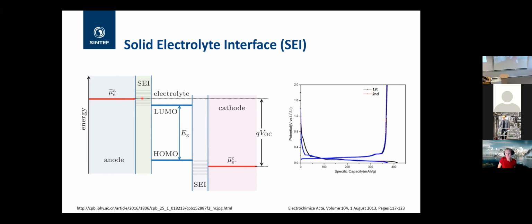So what happens is that when you charge it, when you take the lithium ions from the cathode and into the anode, when you go beyond a certain potential, which is shown here, below about 1.1 volts, you start to decompose the electrolyte. And you can see here on the black line, which is the first cycle, and the blue line is the second cycle. So the black line right here shows where this SEI, solid electrolyte interface layer, is formed.